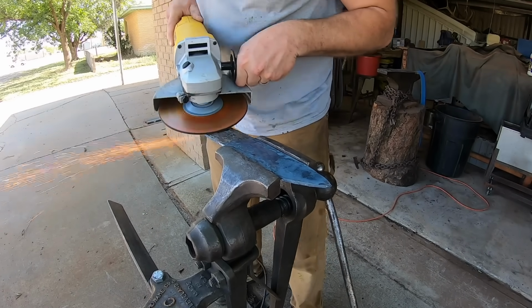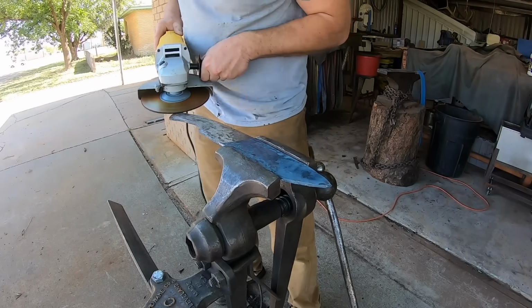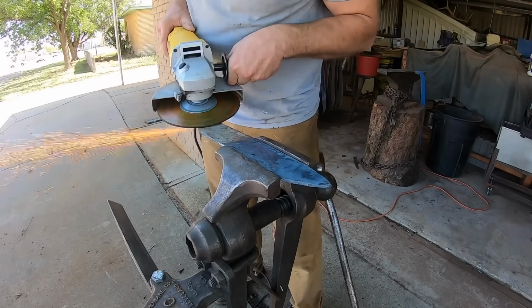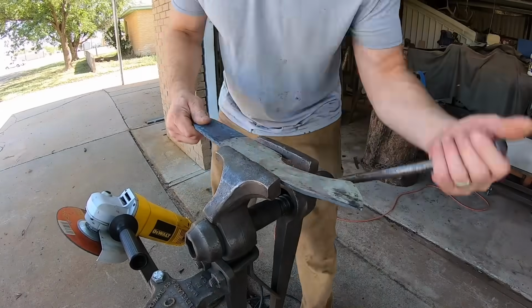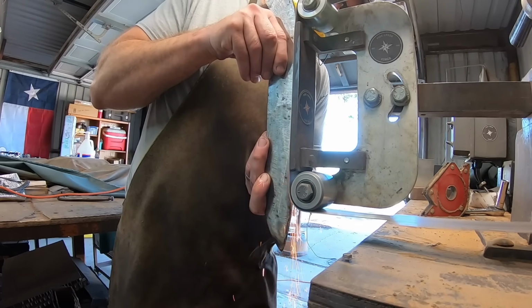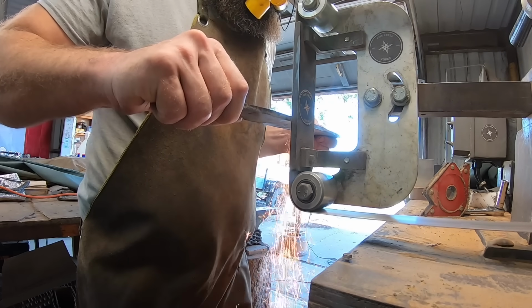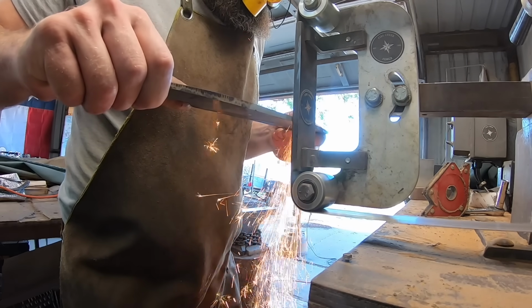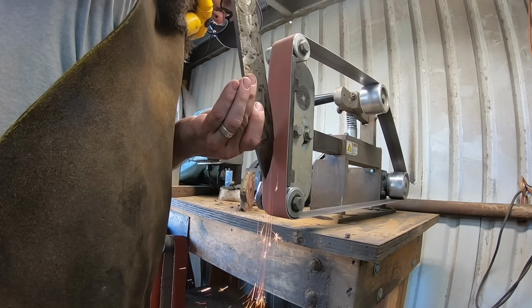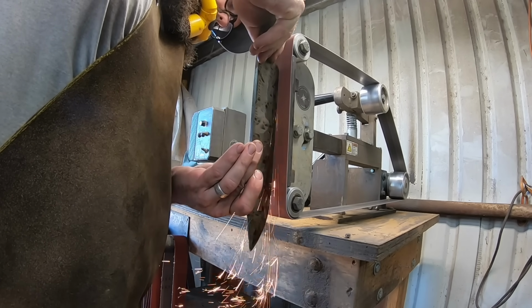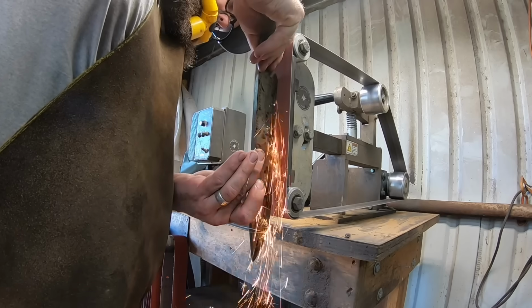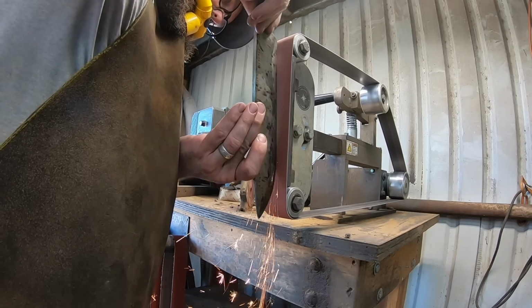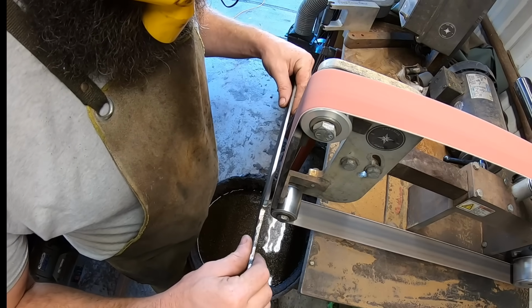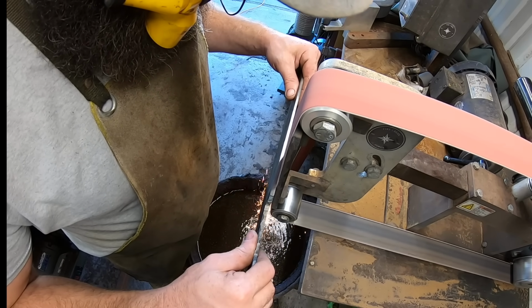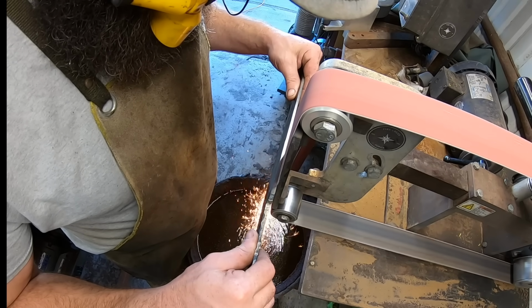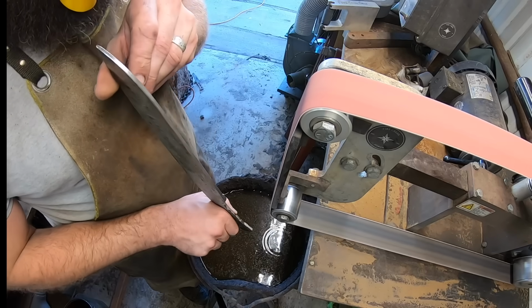The next thing we've got to do is go ahead and grind off all of this scale. And something I did off camera here is after I normalized it, I also did a process anneal on it. So basically a divorced eutectoid anneal, which simply means it's softer and somewhat spheroidized. The main reason for that is to put the carbon back into a better place inside and get it ready for another quick thermal cycle before we do the quench cycle. But also that allows us to grind this pretty easily and to drill the holes in the tang because it's relatively soft at this point.